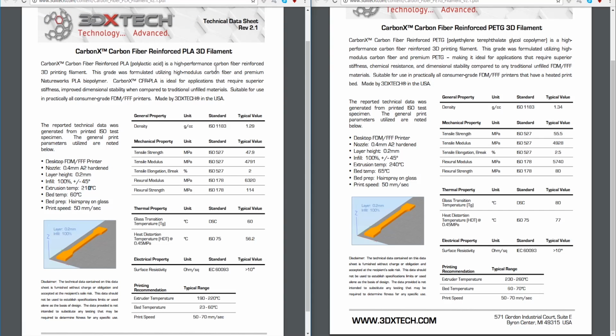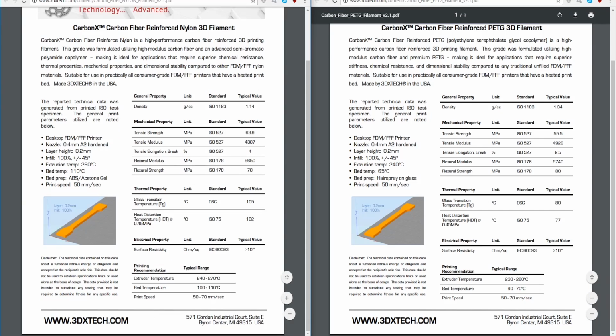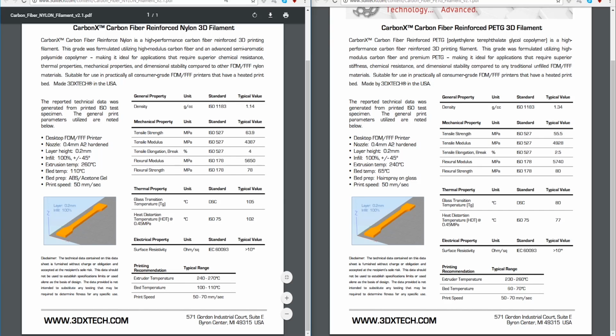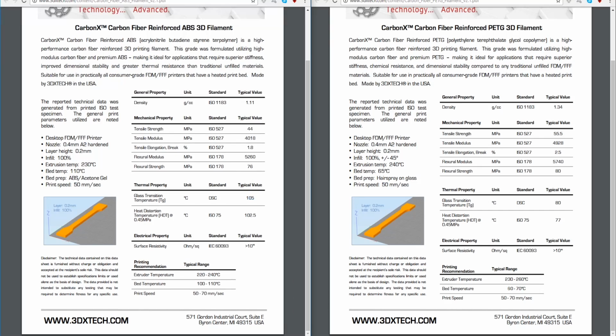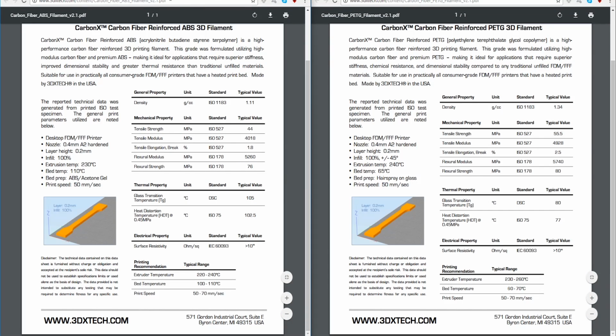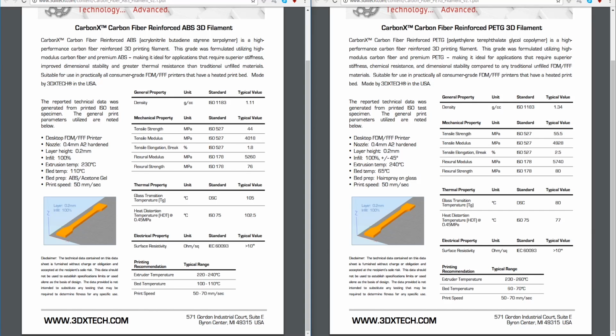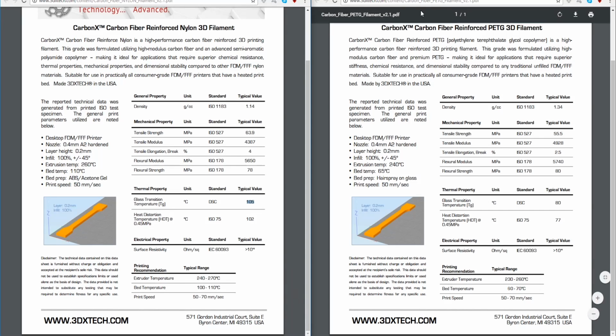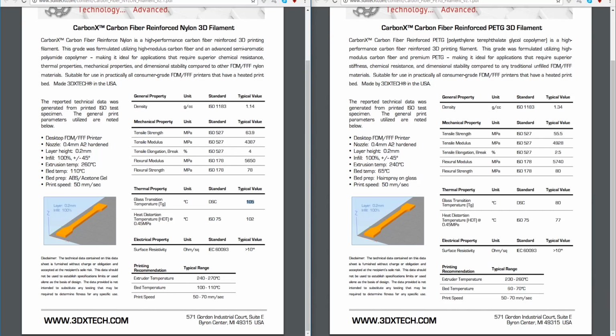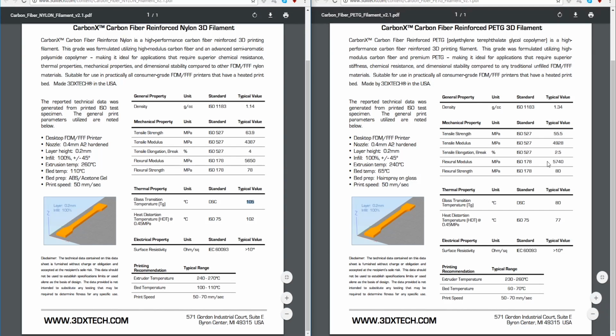Nylon: heat load, high strength, almost as high as PLA, and also high flex. So basically all good properties right there, very balanced, but requires a lot of different specs to print. So if you can't print that, and I need a very high temperature, then I would do ABS. And then basically the PETG is in between the carbon fiber PLA and the carbon fiber nylon. So I'd pick the PETG if I couldn't print nylon or ABS, pretty much. But other than that, I would go with the nylon.